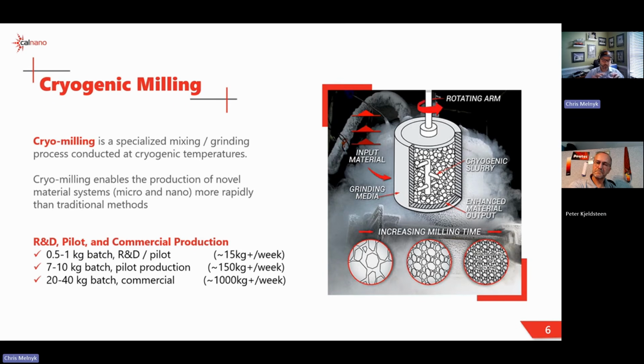So essentially it's kind of like making saltwater taffy, if you're familiar with that process, where it's folding and blending over itself over and over. So you get this very thin layer, and the powder is actually a coating that's being formed on all the media. And that coating is being formed, and those particles are being mashed and smeared with extremely high deformation onto the metals. And then that coating breaks off and becomes powder, and repeat and repeat and repeat. And that's how we're actually able to produce nanostructured materials.